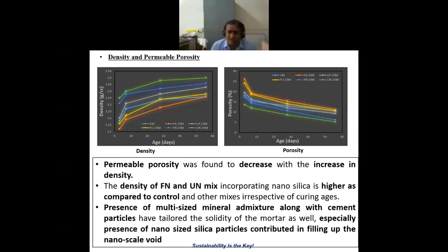Similarly, the density and permeable porosity, these are just plots actually. Density let us not discuss, but let us see the permeable porosity, because this is very important for us. Now you can see here that nanoparticles and ultrafine fly ash combination gives you the least porosity. Here the porosity in the initial stage was more than 25 percentage for the fly ash 25 percentage mix. Now it is reduced to less than 15 percentage. So that is the beauty of adding nanoparticles. And even at a later age, that is 56 days, it was almost 15 percentage, but reduced to close to 5 percentage. So that is the significant reduction of the permeable porosity.